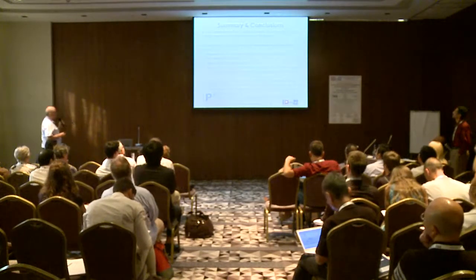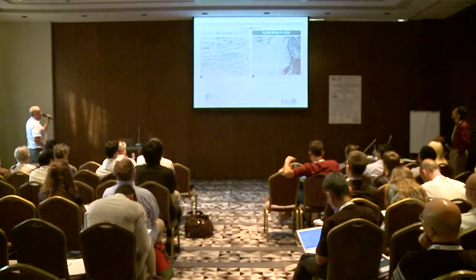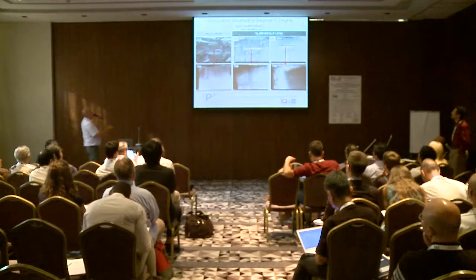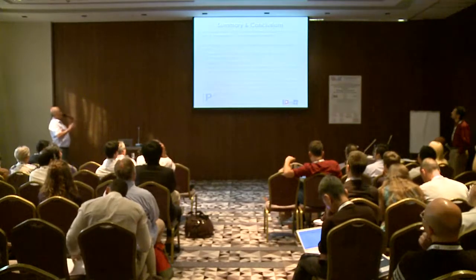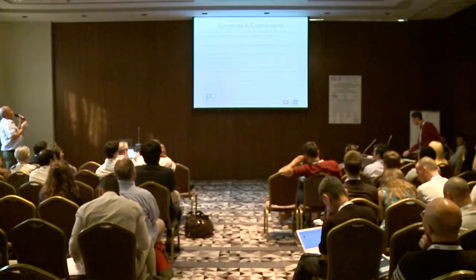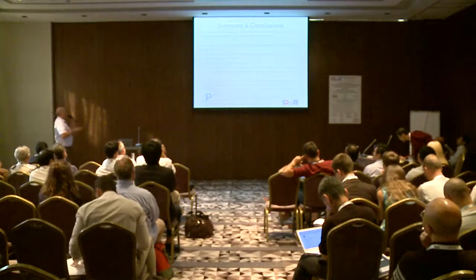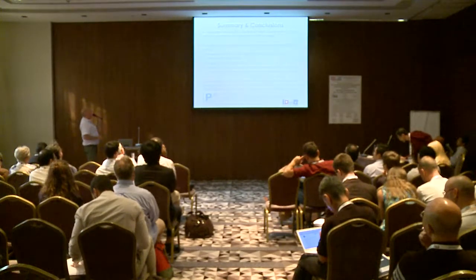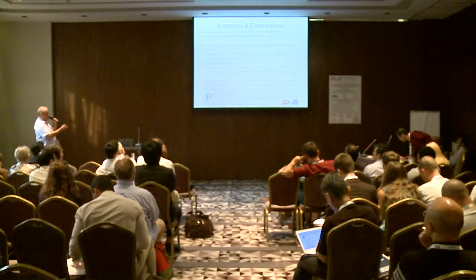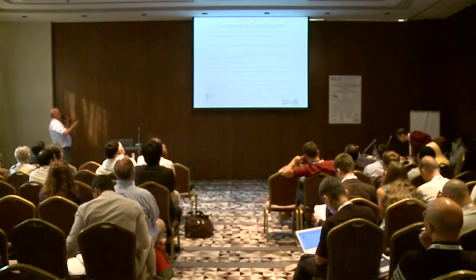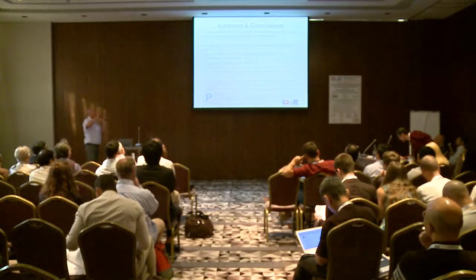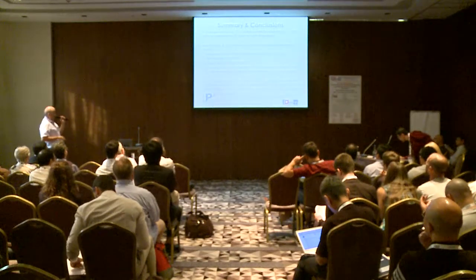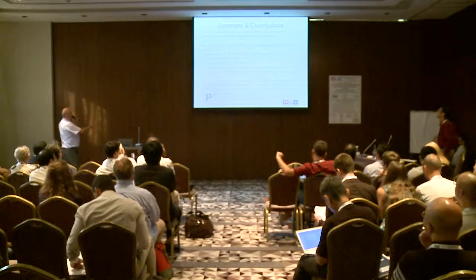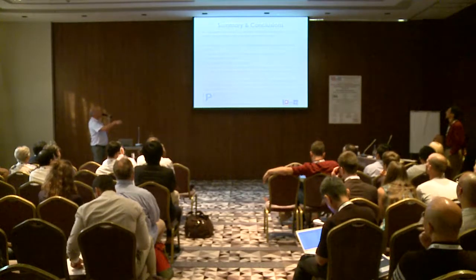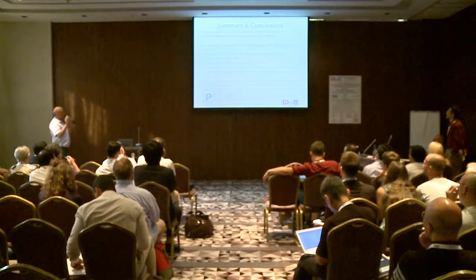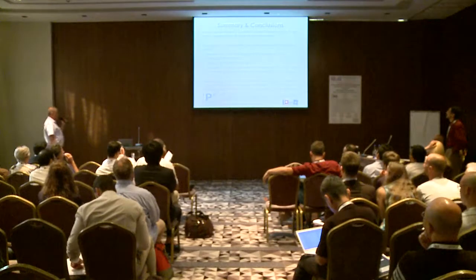So let me summarize my talk. We have seen that we have a fatigue crack growth enhancement in this commercial pure iron with a dependency on gas pressure and frequency, with the presence of three characteristic regimes. A first regime where we have no fatigue crack growth enhancement despite this change from a transgranular to a fully intergranular cracking mode, a transient regime, and a highly saturated regime characterized by the presence of coarse brittle striations.